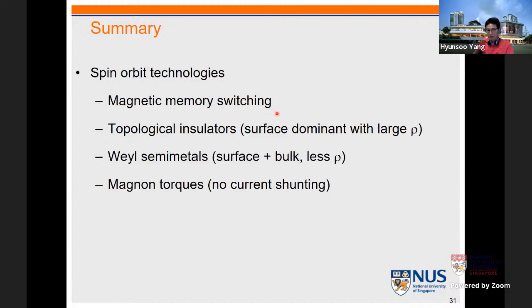Can be applied to magnetic memory switching applications using these topological materials, starting from topological insulators. Even though we were able to find a very effective large spin Hall angle, there is large resistivity involved, which eventually leads to large power consumption. So then we move to Weyl semimetals. We can utilize even bulk spin-orbit torque, and with less resistivity, but still we have current shunting issues.